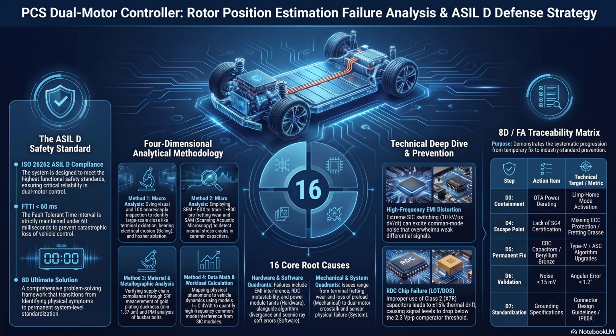Yeah, and if the software's hard-coded panic response is to execute a 3-phase freewheeling shutdown, meaning it just opens all the high-voltage switches to protect itself, that generated current has nowhere to flow, except right through the anti-parallel diodes of the SiC MOSFETs, straight into the DC link capacitor. And the bus voltage skyrockets exponentially. It goes from 800 volts to over 1200 volts in milliseconds. And once that voltage exceeds the avalanche breakdown threshold of the silicon carbide semiconductor lattice, the PN junctions are completely destroyed. The modules literally vaporize. The inverter is essentially a bomb that just detonated itself because it misread a single data point. This is precisely why building an ASIL-D architecture is so incredibly complex. You are managing the physical mechanics, the electromagnetics, the quantum-level data integrity, and the software's psychological response to failure simultaneously.